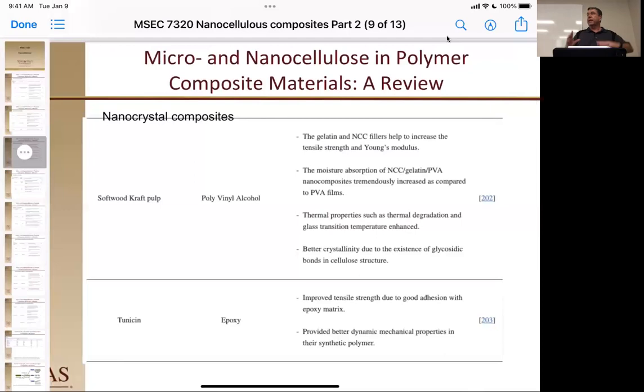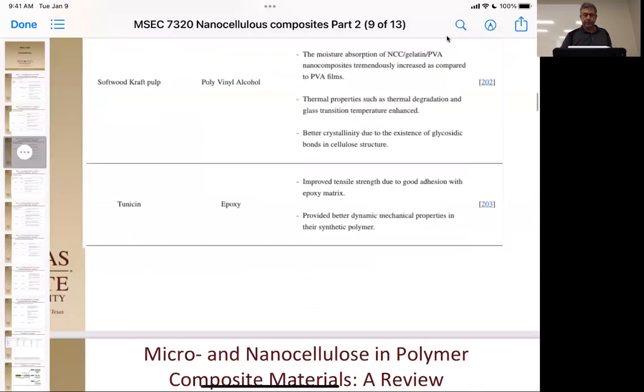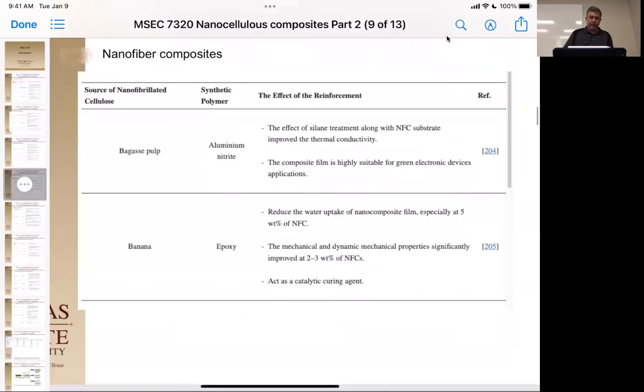Epoxies are pretty brittle, so having any kind of flexible filler is probably helpful. Okay, and I don't even know what the bagasse pulp is, but they saw the same things there. Not sure why they say aluminum nitride, but they're using that as a cross-linking agent. Aluminum can bond three times to anions, so they might be using it as a cross-linking agent, so there's not technically a polymer here. It made it highly suitable for green electronics, and improved thermal conductivity. Again, probably because of the cross-linking between the two.